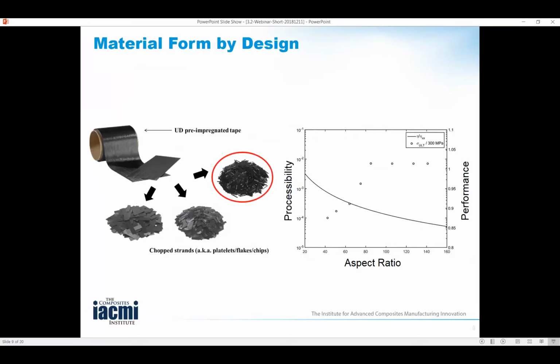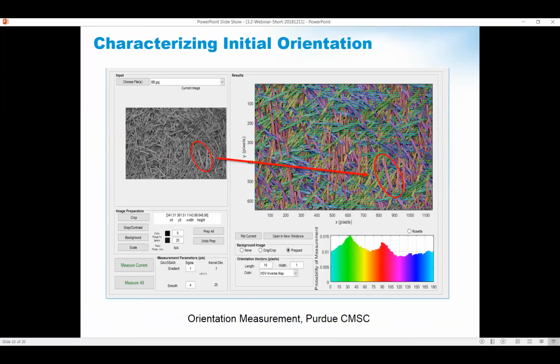Now, it turns out that for this material system, Dow designed it such that they have a very good blend between processability and performance. The aspect ratio of these platelets is such that they maximize the performance while maintaining maximum levels of processability. That's step number one. Number two is understanding the orientation.